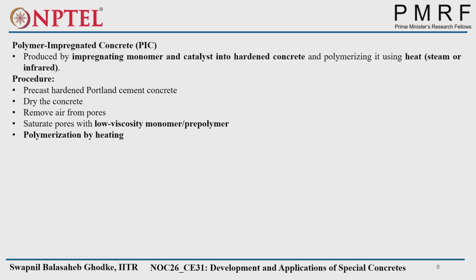Low viscosity monomer. Why do we have to use low viscosity? If we want the pores to be fully occupied, the viscosity of the monomer should be low. If it is high, we have to pressurize more, and it requires more advanced pressure equipment or pressure conditions to get into the pores. And the polymerization will start by the heating process.